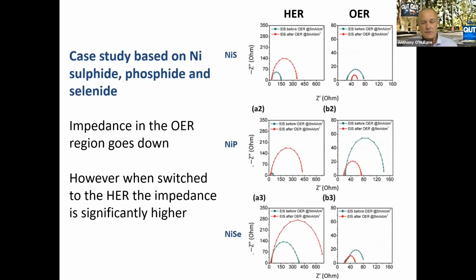So we can see here from the impedance spectrum, for the oxygen evolution reaction we actually got a decrease in impedance, telling us that our oxygen evolution reaction performance was getting better. But for the hydrogen evolution reaction, the impedance went significantly up in all cases, for the sulfide, the phosphide, and the selenide. So any oxidation of that cathode is very detrimental to the hydrogen evolution reaction, and certainly increases the overall impedance of that particular system.